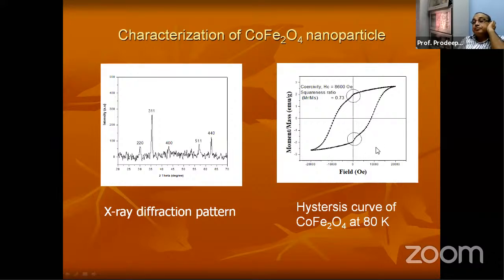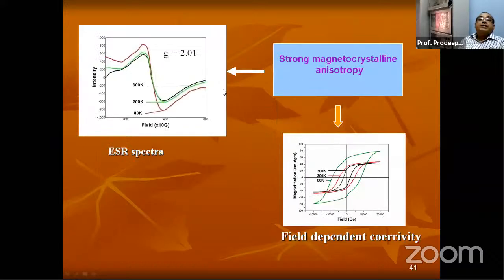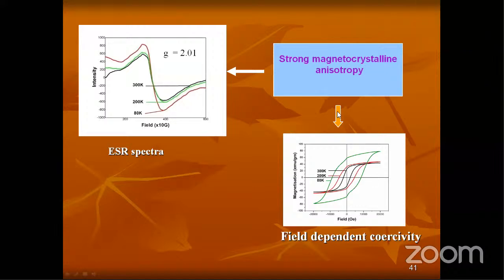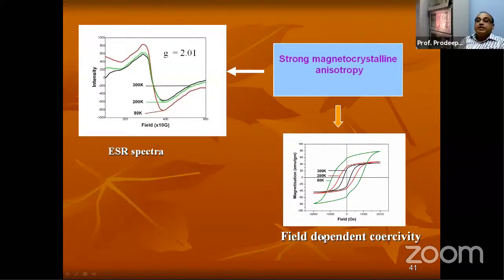They were magnetically active. They were magnetic. They have magnetic character. And so this is the ESR spectra. So this shows a strong magnetocrystalline anisotropy. It shows a field dependent coercivity. It is all magnetic.